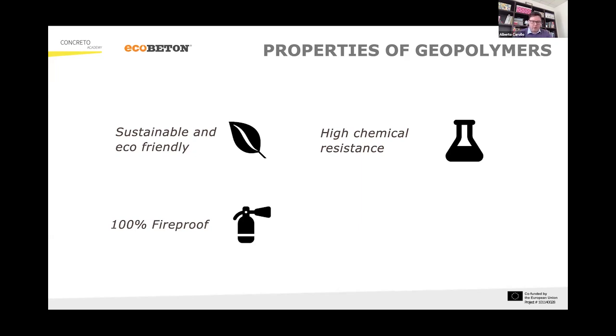Geopolymers can resist up to 1200 degrees C without any damage, just to have an idea. And the mechanical properties are very high. Usually it depends on the formulation, but we can consider them double those of normal concrete, to have an idea.